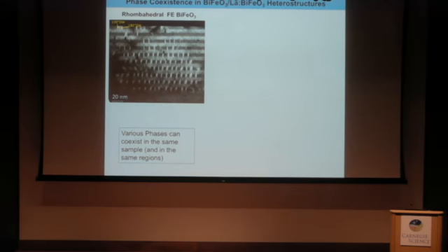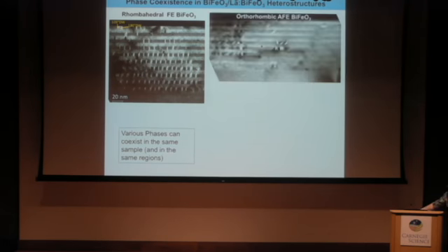We actually see a huge zoo of possible ferroelectric or polar systems, and they can coexist. So clearly, this interface engineering is right on the edge of some instability with the polar ordering that you get. And so here's an example where we have these nice 180 degree domain walls throughout a whole film. And here's a region where we have this orthorhombic antiferroelectric stripe phase.